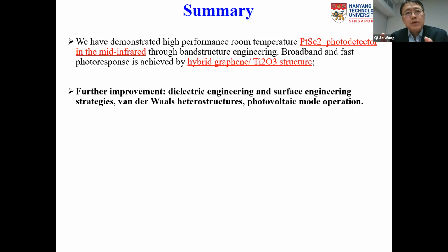And the improvement can be done through defect engineering and dielectric engineering, for example, passivation of boron nitride or other dielectric layer to reduce, for example, Coulomb interactions, improve mobility, to further improve the device performance, or using van der Waals heterostructures, as just mentioned. We already have some results demonstrated, not shown here today, all in the photovoltaic mode operation, where the dark current can be significantly reduced.